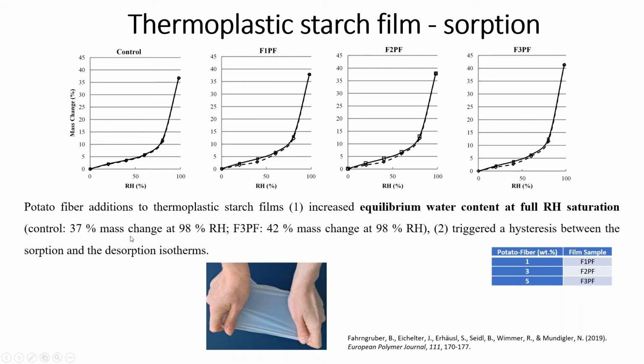And so in that case, potato fiber additions were added to the thermoplastic starch films to improve properties, including mechanical properties. And it increased the equilibrium water content at full saturation. You see that point is moving up a little bit. So that was changed. And it also triggered hysteresis, because that addition created nanopores in the material. So that's quite valuable from an industrial point of view to understand the material, because the customer experiences some properties, and of course you need to understand what you are developing. So that's one example that we published in 2019 with different contents of potato fibers in the thermoplastic starch, processed by blow extrusion, and then we tested films that we cut out from those foils.